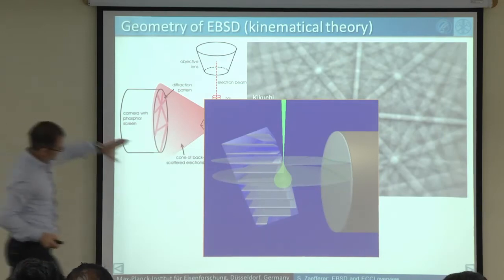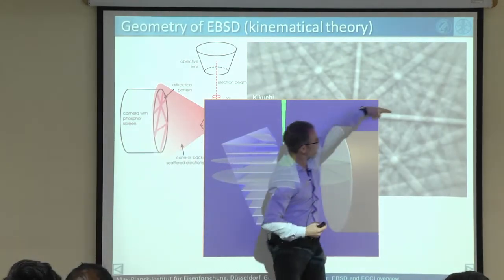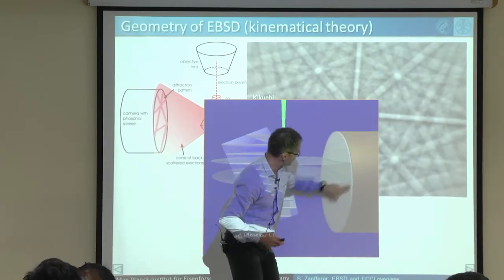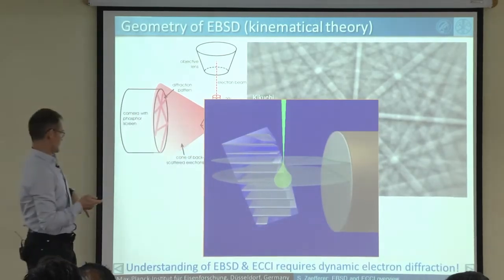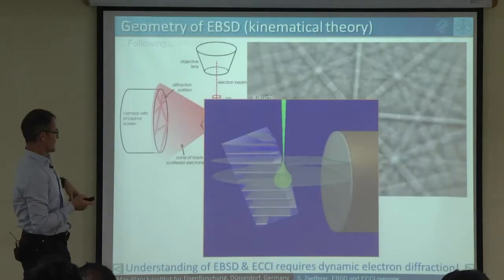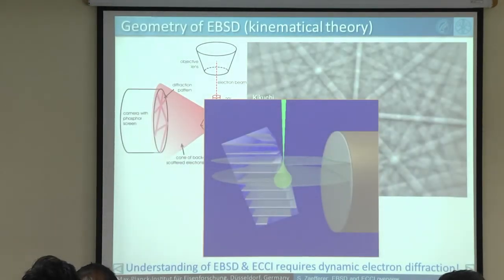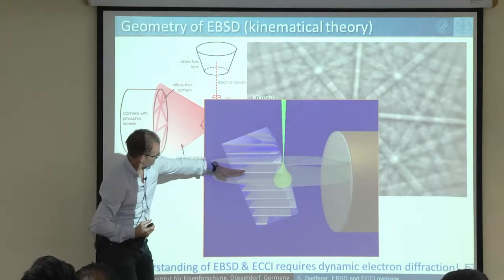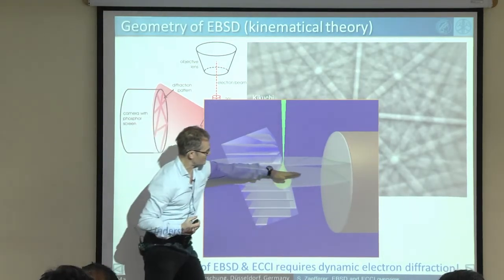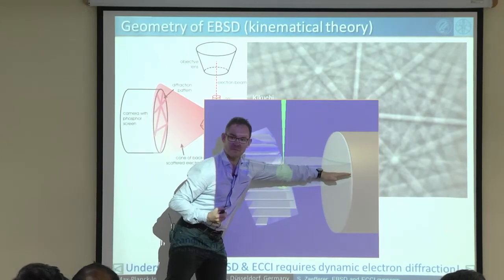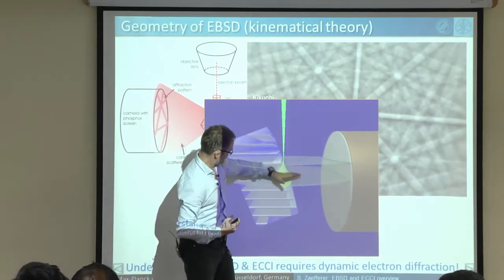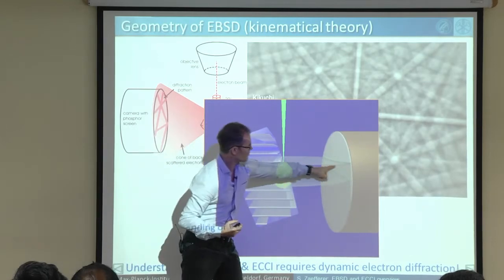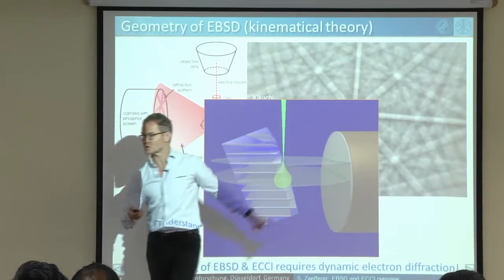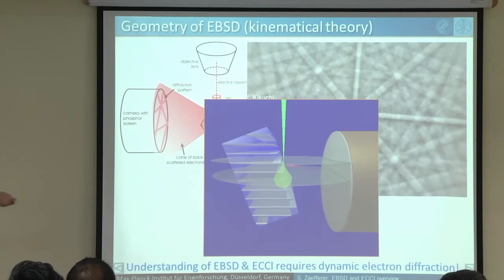And actually very nice is, so these are these two cones. Actually, this is one side of the band and the other side of the band. So this is making one cone and the other cone. That's a shortcutted image. In principle, if you take these planes here and extend them all the way to the phosphor screen, then you would find the position of the plane makes approximately the middle line between these two Kikuchi bands, between the two Kikuchi lines, sorry.